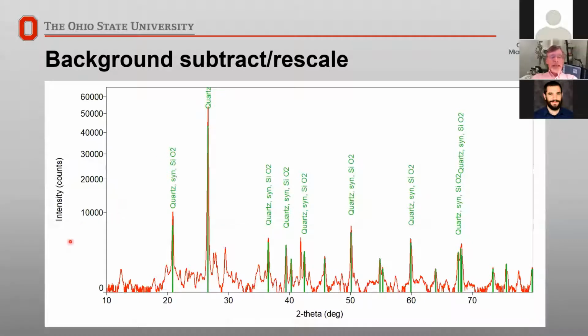And I made a guess. I said, well, soil tends to have a lot of silicon and oxygen in it, so let me look for silicates. And I then put that elemental constraint into the database, and it returned that I had quartz in my sample. And if I look at where the peaks are from my library, they match up very, very well with the peaks that I have in my scan. So I then went through and I looked for other possible elements and so on.